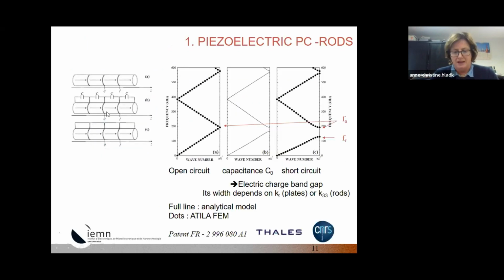So this is the result for the analytical model. In the first case, on the left, all the electrodes are in open circuit. So in that case, you have the propagation in the material. It is like a homogeneous material. Then you have a capacitance connected to each rod, and in that case, you see there is a small band gap that appears. And then, if all the electrodes are in short circuit, you see a band gap at the boundary of the Brillouin zone. The lower frequency of the band gap is the resonance frequency of the rod, and the upper frequency of the band gap is the anti-resonance frequency. It means that the width of the band gap is related to the electromechanical coupling factor of the material.